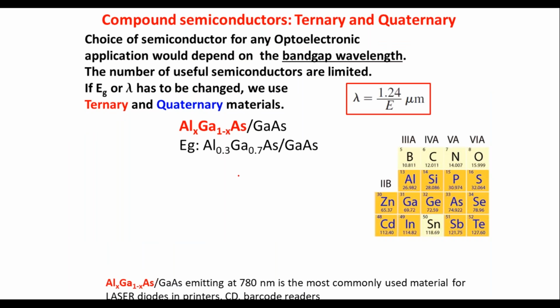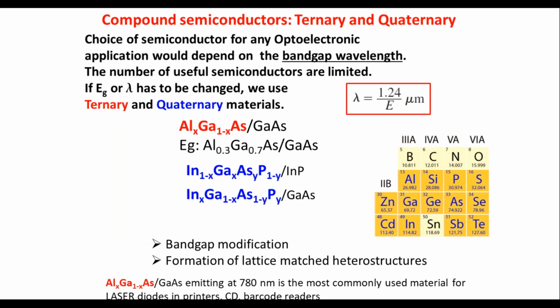There are in fact materials called ternary semiconductor materials. For example, aluminum gallium arsenide and gallium arsenide. This is one material combination. The other material combination is indium gallium arsenide phosphide. This is the other material combination. This material combination is the one which is going to support 1550 or 1300 nanometer, and therefore for this particular switch we'll focus on this material.